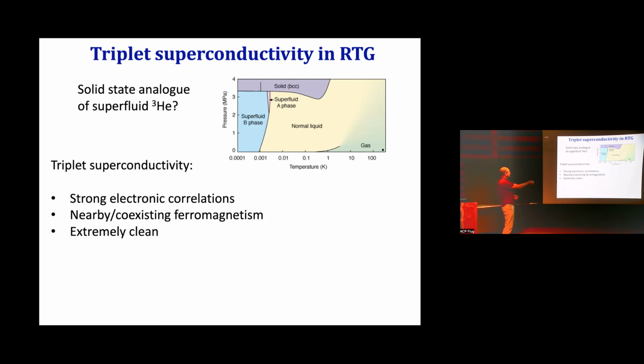That's because to get spin triplet, you really have to get a very, very special combination of factors. You need very strong correlations between electrons, very strong interactions. It's good to have a nearby or even coexisting ferromagnetic state. And the system needs to be extremely clean.